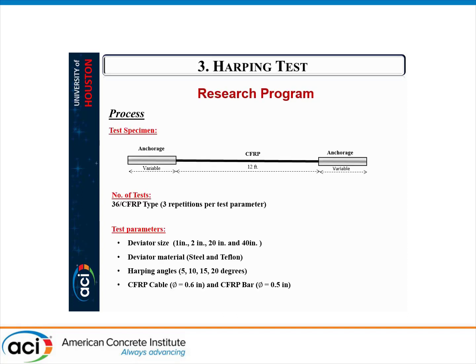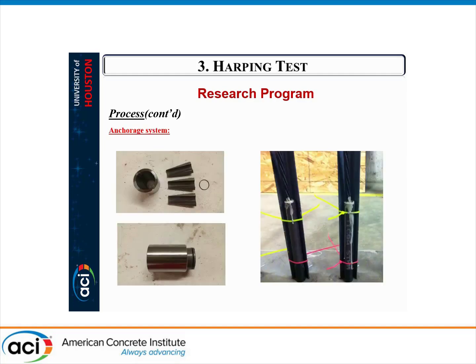The test specimens, again, are CFRP cable and bars anchored at the end. We have 36 specimens per CFRP type. The test parameters are the deviator size, deviator material, harping angles varying between 5 to 20 degrees, and the type of CFRP. So the process starts again with production of the anchorage system, where again we have the potted type anchors filled with highly expansive material. In this special case, we have the application of wedge and sleeve grips to apply the prestressing force.